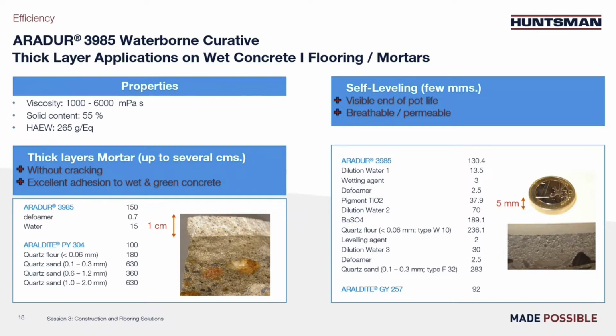So on the left side, there is an example of a thick layer mortar, about 1 centimeter thickness, and you can see the simple formulation. On one part, the hardener is formulated with water and a defoamer, and the second part is a pure Araldite PY304, formulated with a blend of different particle size quartz. It helps to ensure good packing and good mechanical properties of the mortar. Generally, the advantage of using waterborne for this application is to reduce the viscosity, allowing a large amount of filler and ensuring good wettability of the substrate. It's also much easier to clean the equipment as you can do it with water.